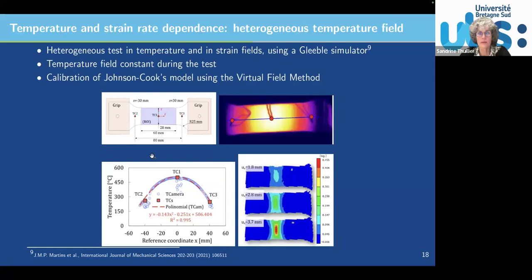And my last example in this part is now mixing strain rate dependency and temperature. So in this case, we used a heterogeneous test in temperature, and a Gleeble simulator was used. So a Gleeble, you have electrical currents going through the sample. So here is your sample, in tension, and you've got electrical current going through the sample, and you regulate the intensity on the temperature that you want to reach. For example, here in the center, you've got thermocouples at this free position, and you regulate your test on the temperature in the center.